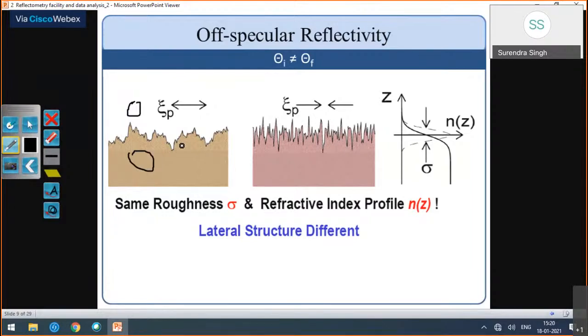How many times a particular height is coming, height distribution we say - for both of them will give the same signal. But you can see from specular reflectivity you will get the same interface roughness, but both interfaces are quite different, I mean they are not same. As you will see, there are different morphologies.